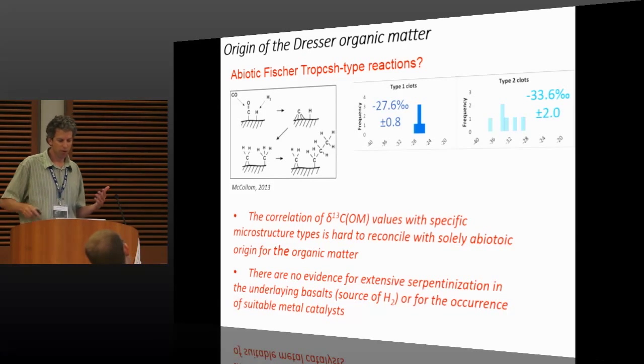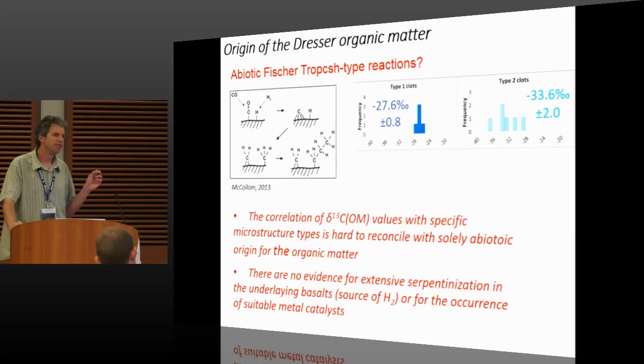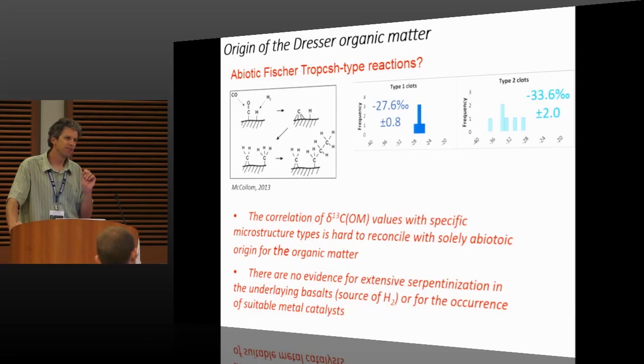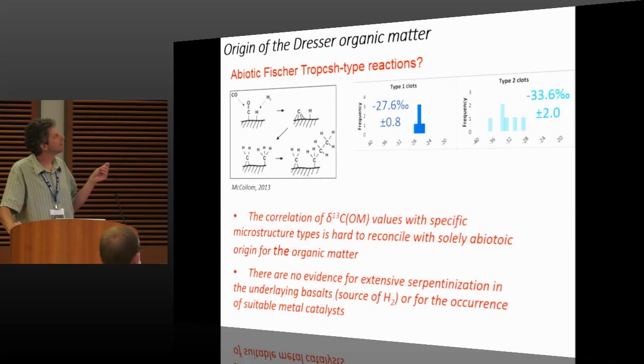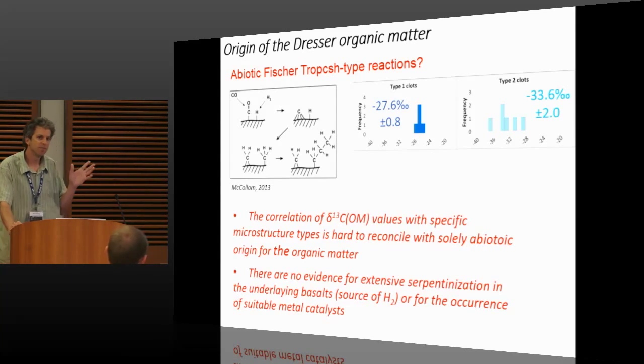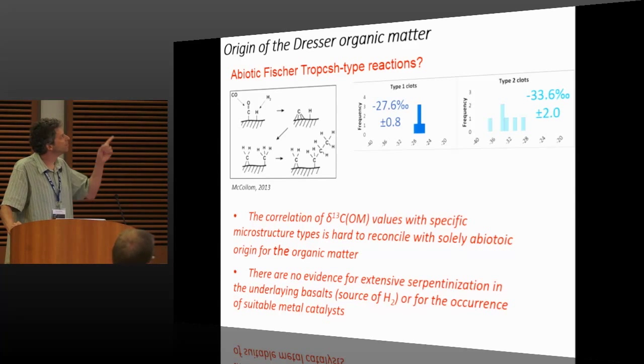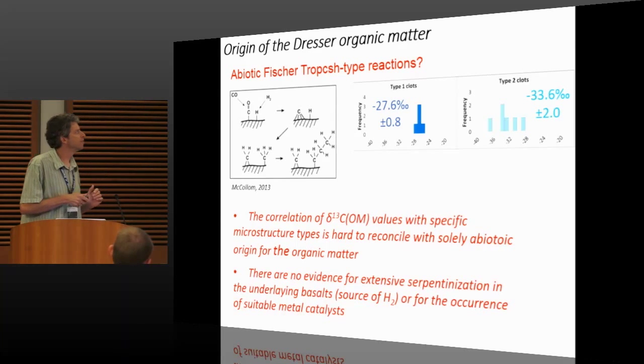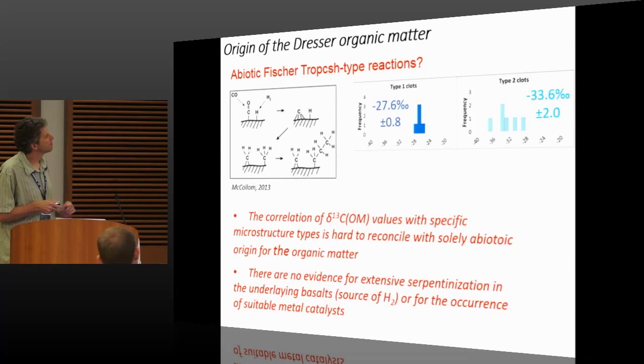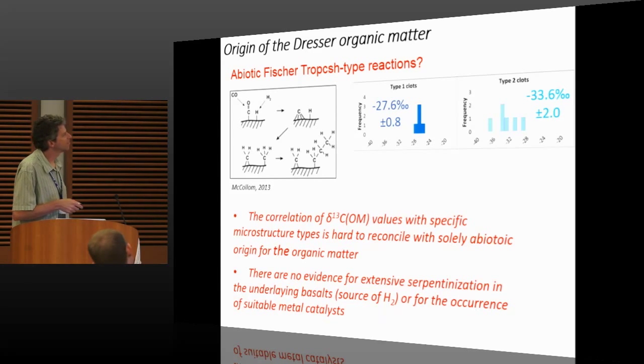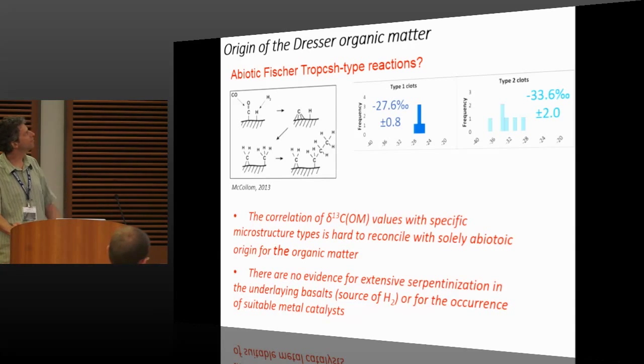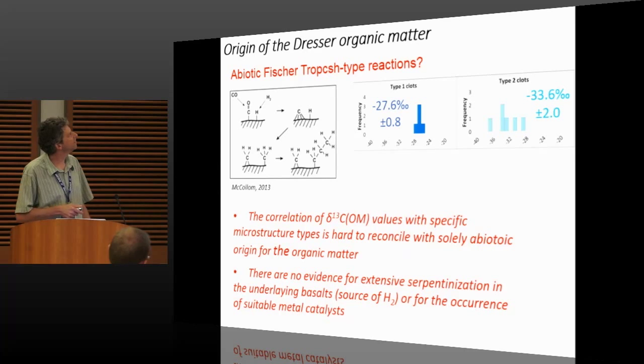However, the correlation that I've seen between isotopic composition and specific microtextural types is hard to reconcile with this process. If the source of organic matter was just simple polymerization of hydrocarbons formed this way, we would have expected it to have a uniform isotopic composition, at least in one single sample, which is not the case. And likewise, there is no evidence for extensive serpentinization in the underlying basalts, which could have served as a source of hydrogen needed for the reaction, or for the occurrence of suitable metal catalysts in the Dresser chert.